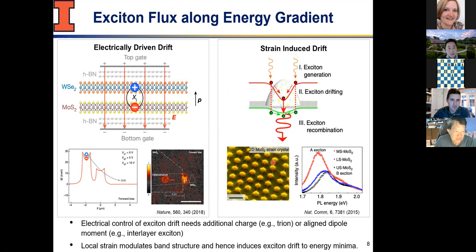But this work required a so-called heterostructure. You can see there are two layers because, if you have just one layer, these excitons are in plane. So basically you have an electron-hole pair in plane, and the vertical electric field is orthogonal to the in-plane dipole, so they don't talk to each other. Whereas if you have an out-of-plane dipole moment by having two layers of 2D semiconductors, a so-called interlayer exciton, you can do that. I won't go into that, but that's how they did this, and it's very interesting work.